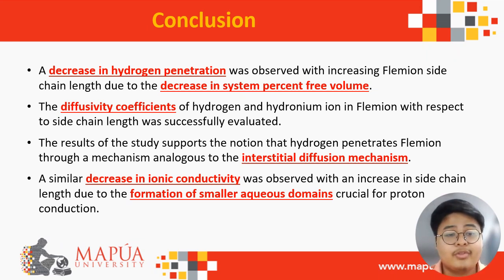Furthermore, the diffusivity coefficients of hydrogen and the hydronium ion in Flemion with respect to side chain length were successfully evaluated. The results of the study support the notion that hydrogen penetrates Flemion through a mechanism analogous to the interstitial diffusion mechanism. A similar decrease in ionic conductivity was observed with an increase in side chain length due to the formation of smaller aqueous domains crucial for proton conduction.